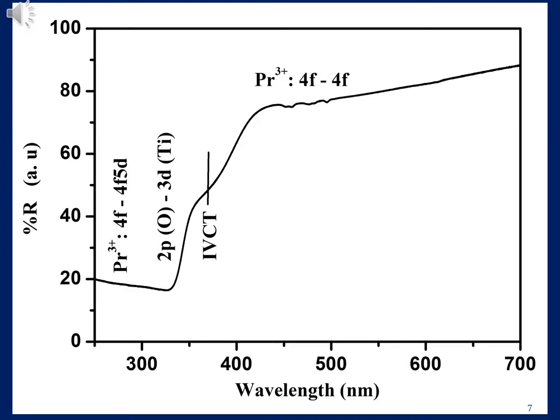Now, for an orthorhombic structure of calcium titanate, the IVCT is below the 3P state because the AB distance is lesser. So is the energy of the shared electron. Now, the IVCT will strongly couple with the 3P state, and all the electrons in that state will cross over to the IVCT. Now, from there they will de-excite to the 1D state and lead to a single red emission from a transition of 1D to 3H electron transfer.